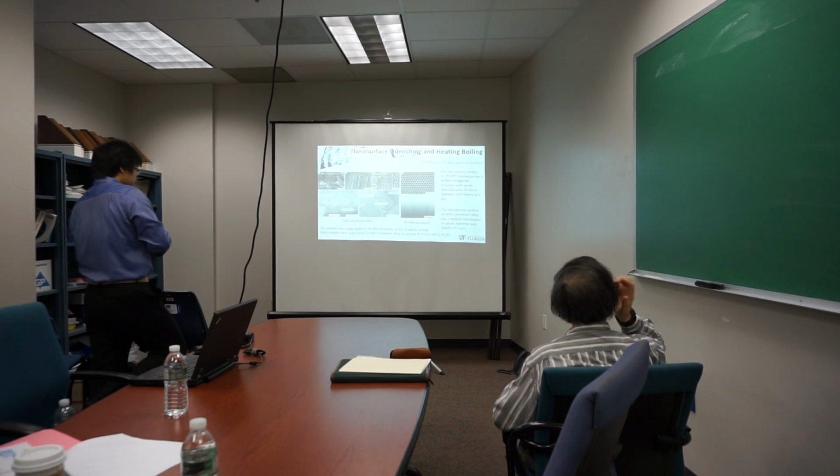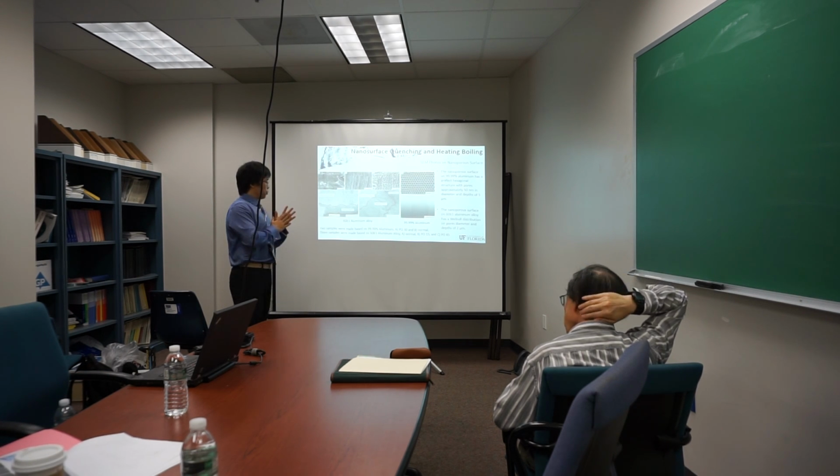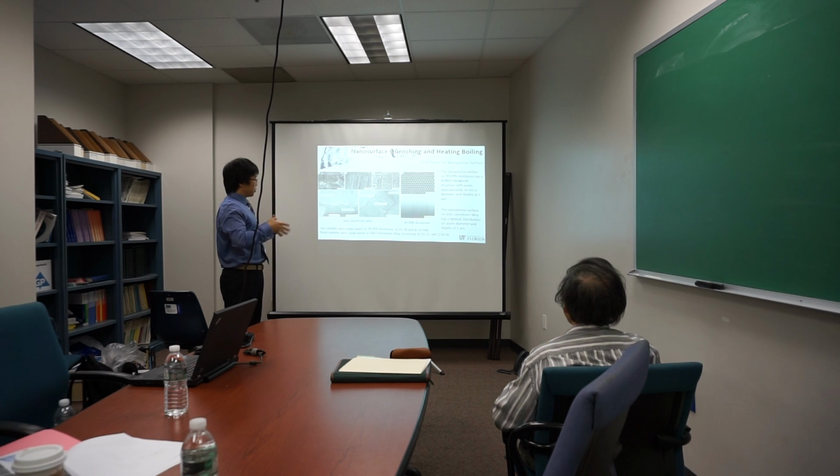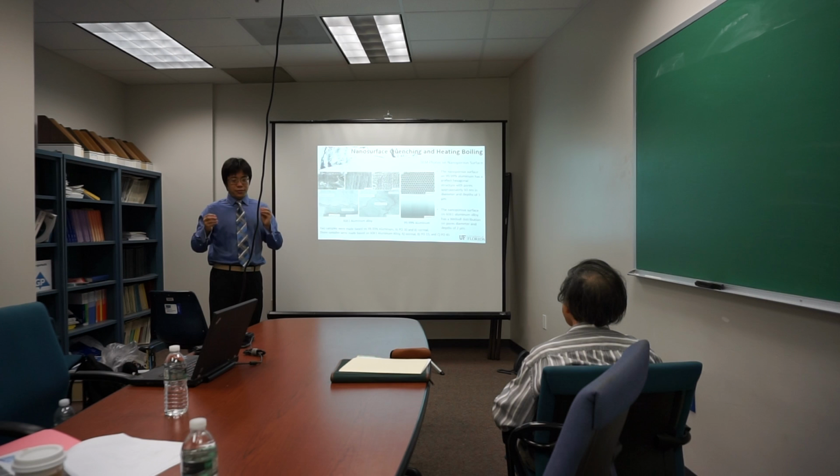And for the surface, I separated into two categories. The first one is 6061 aluminum alloy, which I'm using right now, and another one is 99.99% pure aluminum. We use the same method to create nanopores on the surface, and because the 6061 only has about 95.85% aluminum, and the others are different elements like carbon and silicon, the nanoporous structure you will see will be different.